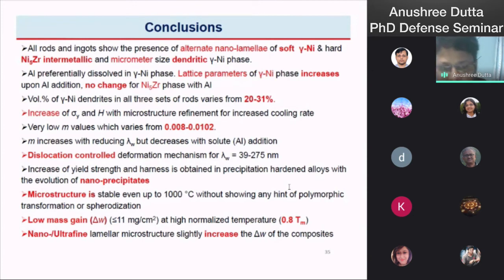With the microstructure refinement for increased cooling rate, very low strain rate sensitivity varies from 0.008 to 0.0102. Strain rate sensitivity increases with reducing lamellar thickness but decreases with solute content. Dislocation controls the deformation mechanism for the entire lamellar thickness region, 39 to 275 nanometers. Increase of indentation hardness is obtained through a precipitation hardened alloy with evolution of nano precipitates. Microstructure is stable even up to 1000 degrees centigrade without showing any hint of polymorphic transformation or spheroidization.